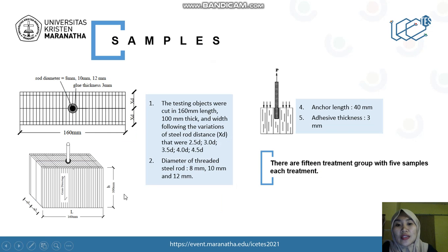Samples. The testing objects were cut in 160 mm length, 100 mm thick, and width following the variation of the steel rod distance or XD. In this picture you can see that they were 2.5 times D, 3 times D, 3.5 times D, 4 times D, and 4.5 times D, where D is the threaded steel rod diameter. And for the diameter of threaded steel rod, we use 8 mm, 10 mm, and 12 mm.